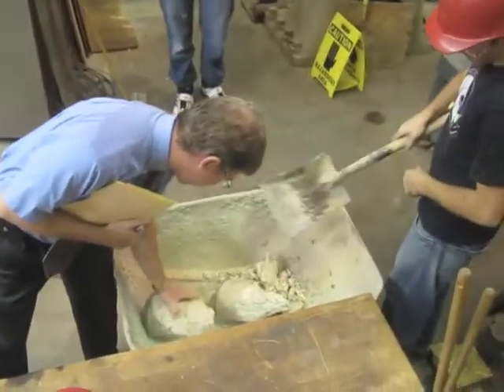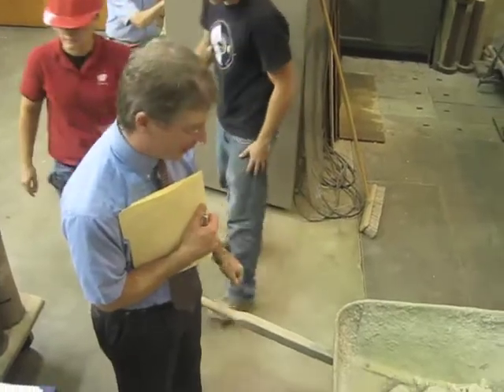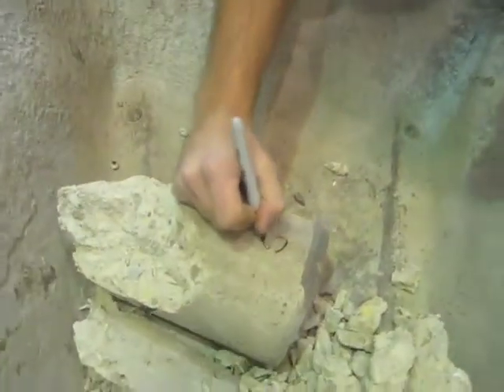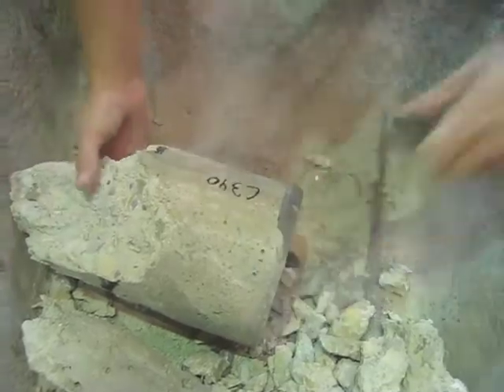As you look at it, it's not very great. It's very dusty — not your ideal concrete specimen by any means. Cement gains strength by hydrating; in other words, it reacts with water. And this specimen here was denied water since it was just out in the air for 100 years.